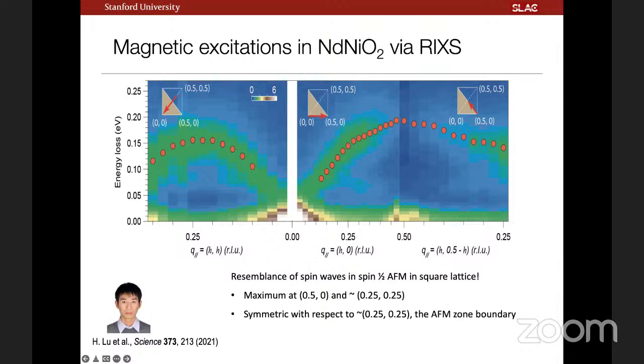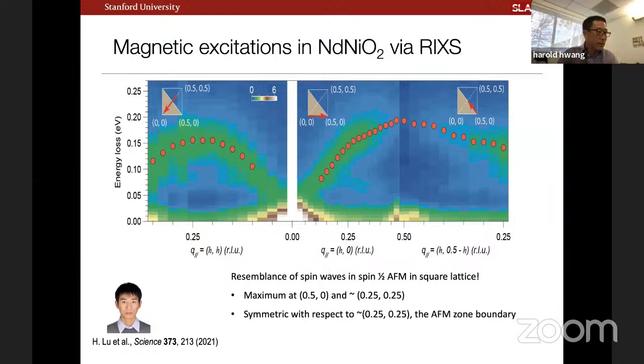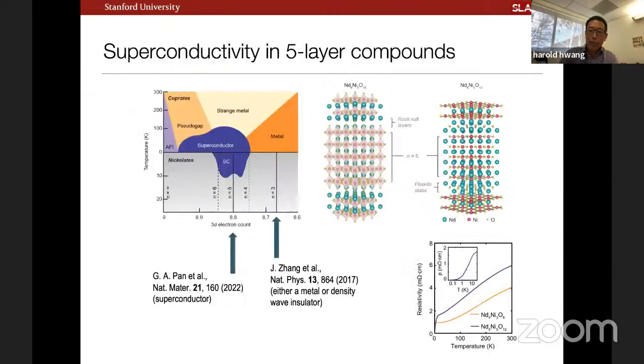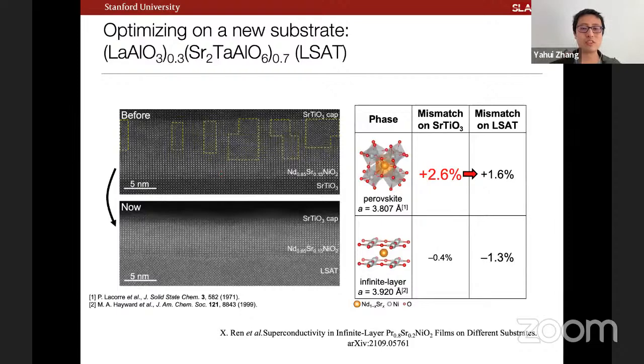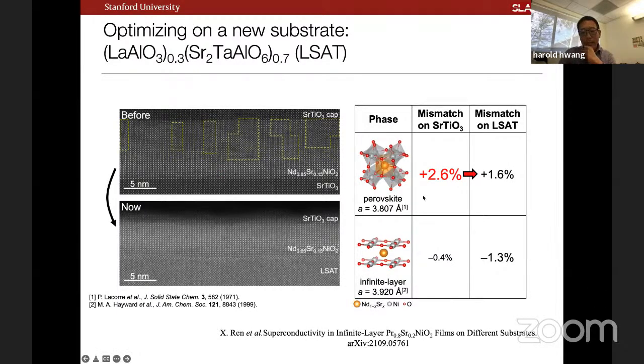I actually have a follow-up question. Do you think it's possible to tune this state from low spin to high spin? Maybe you could just tune the crystal field splitting in some way. Certainly, that's a very interesting direction, whether via substrate strain and so forth, one could go after these things. I think it should be possible. We're not there yet. The issue is the following: so long as we're constrained to using substrates so far, you have about a 3% lattice mismatch or lattice change between the perovskite and the infinite layer phase.